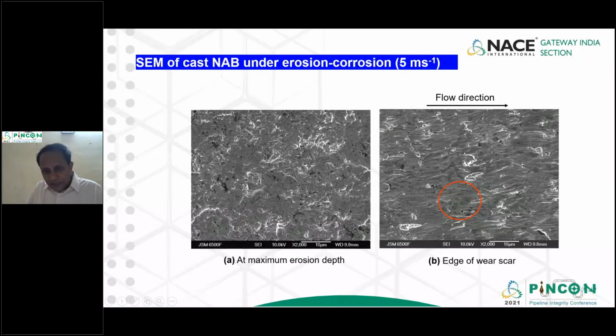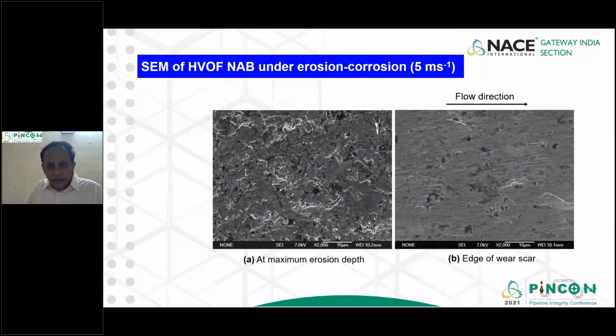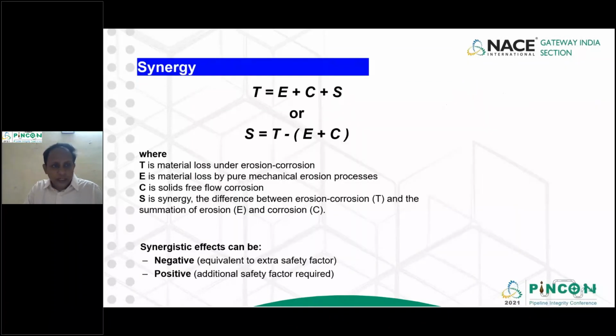We should talk about the alpha phase getting here, and this is a wear scar happening in the direction of the flow. But when it comes to maximum erosion depth, that is when a sand particle is impinging, it's giving plastic deformation. We have seen the same thing here. One directional, the liquid is hitting along with the sand, and it's creating the wear scar.